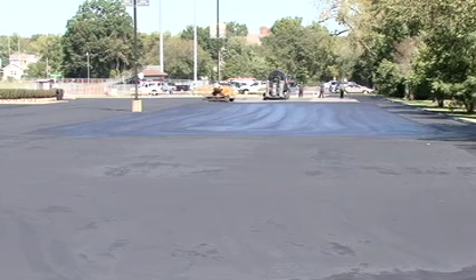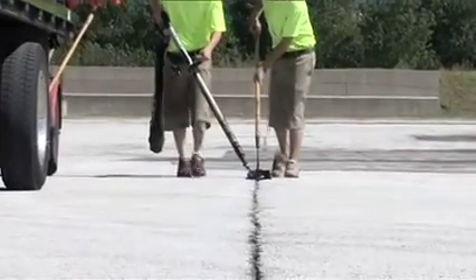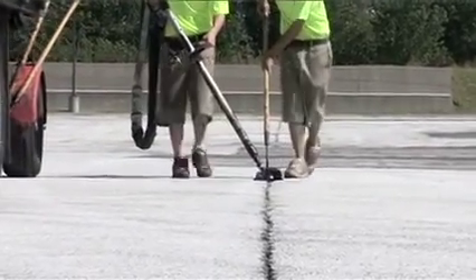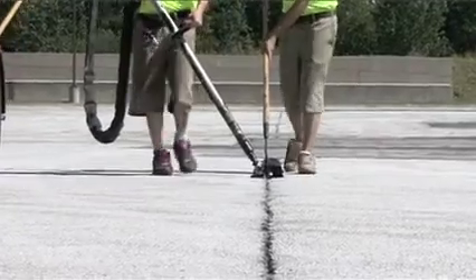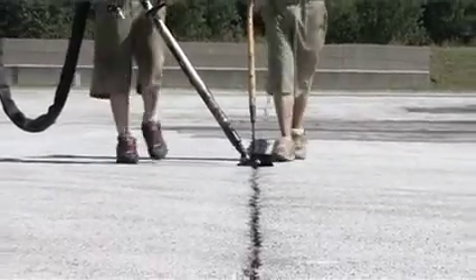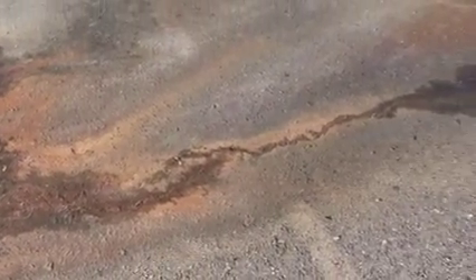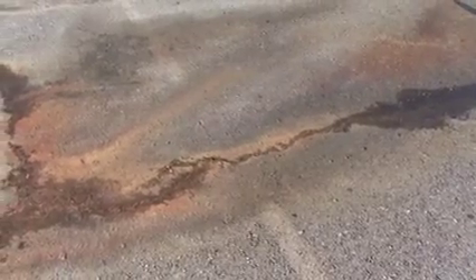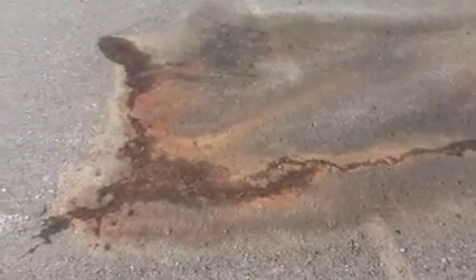Our form of maintenance is generally to suggest crack sealing first if there are small cracks. Again, the ultimate job of maintenance on the asphalt is to keep water from getting to the subbase. Here in our region in the Midwest, we have a lot of clay underneath the asphalt. We don't stabilize the base under the mix very well, other than clay. If we get water into that clay, the clay becomes soft and it starts to move. And if you have traffic on top of that, you're going to start to get cracks. If the cracks develop and water continues to go through them, that will eventually lead to potholes.